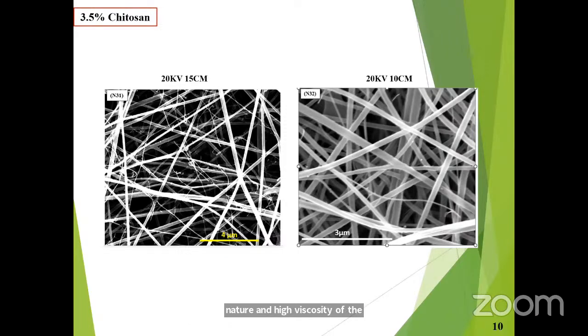Furthermore, a high concentration of chitosan increases the amount of strong hydrogen bonding between amine and hydroxyl groups of chitosan molecules and hinders the flow of the polymer solution, which yields unspinnable results. Therefore, we further optimized the experimental design and tried a 3.5% chitosan concentration for spinnability.